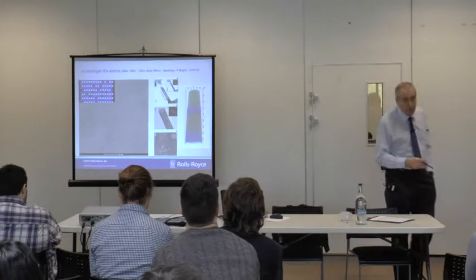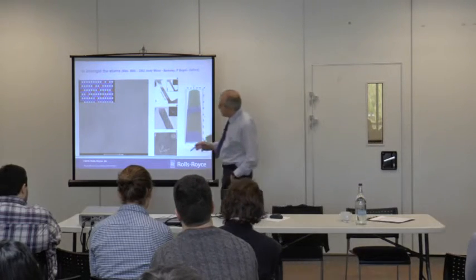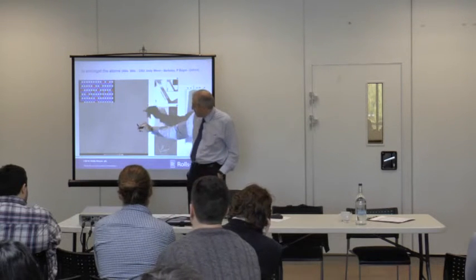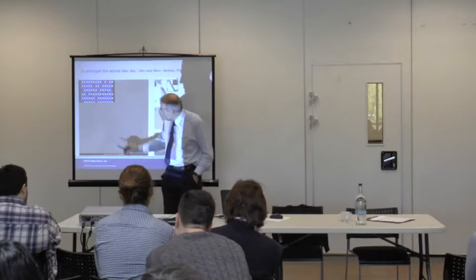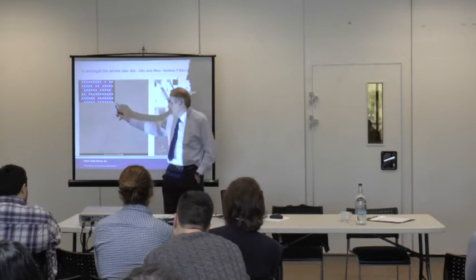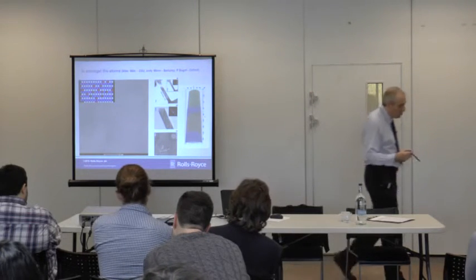Transmission electron microscopy's gone through an absolute renaissance even in the last 5 years. So these are ultra high res TEM images. It's an HCP crystal structure. They're columns of atoms that are imaged. And if you can kind of believe me, you've got a thing in the middle there that's actually a region of short range order where we've got Ti3Al forming, which again significantly alters the properties.